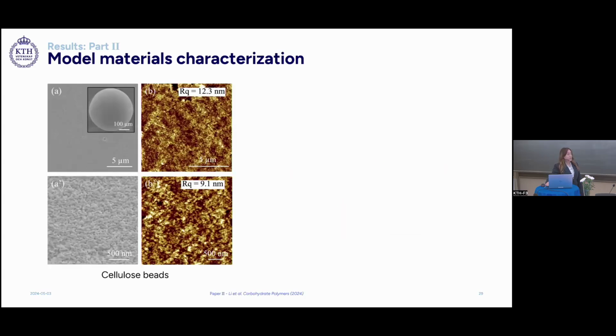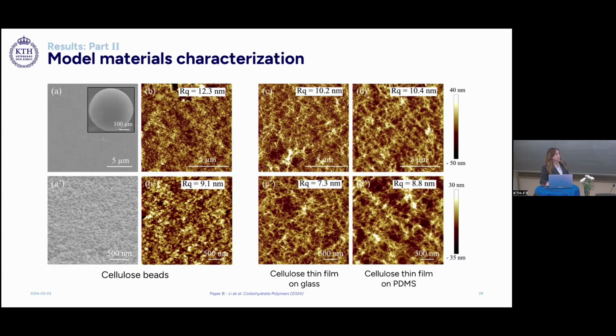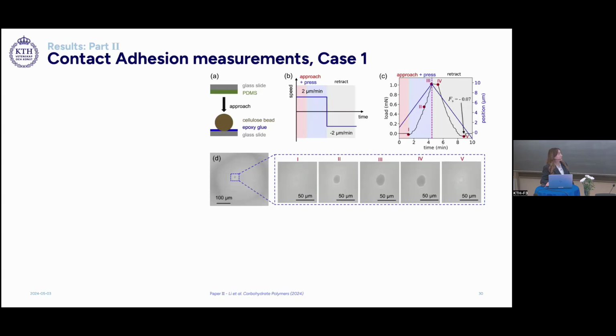And the morphology on the surface of the beads, as well as the films, were analyzed using SEM and AFM. And we can see that the surface roughness is slightly higher on the cellulose beads, and we have an open network of the cellulose films, which is not affected by the underlying substrate.